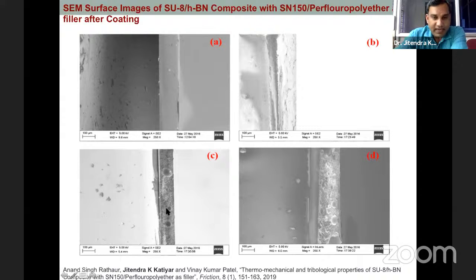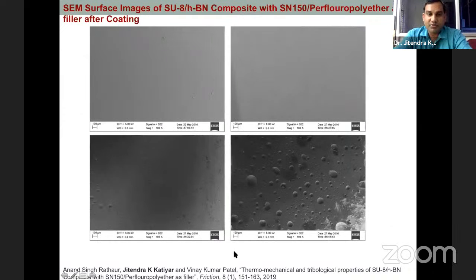Also, if I have added some liquid fillers inside the matrix, we can observe whether they are dispersed throughout the coating or not. We can analyze that with this SEM micrograph. When we added the liquid lubricant inside the solid matrix, SU8 plus hBN, hexagonal boron nitride, we can observe the liquid perfectly dispersed throughout the surface, due to which it gives a lower friction coefficient and high wear resistance. So this is the application of scanning electron microscopy.